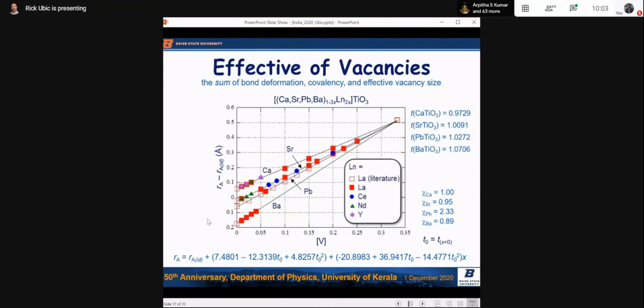I don't know if that's a good term. It's what I've been using for the past 5 years or so. That's what's called the bond deformation term. And over here is our vacancy size term. So if there are no vacancies, this goes to 0 because x is 0 and this vanishes then, right? So 3 components: Shannon, bond deformation, vacancies in general are the components of the RA.